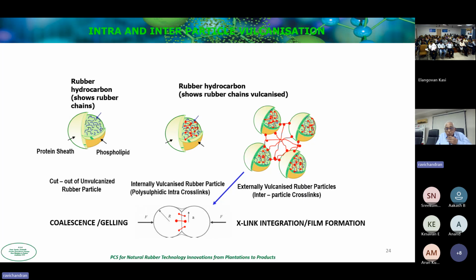And then you can see in the middle, when we have pre-vulcanized the latex, the red, we cross-link the latex inside the particle. We allow the dispersion to enter into the particle by suitable chemical modifications of the surface, and it enters the particle and it vulcanizes the particle. That's the intra-vulcanization within the particle. But there's also from the serum, the sulfur will also cross-link between particles. So you've got the interparticle vulcanization also.